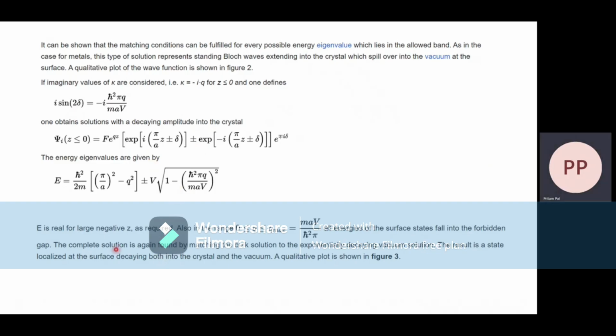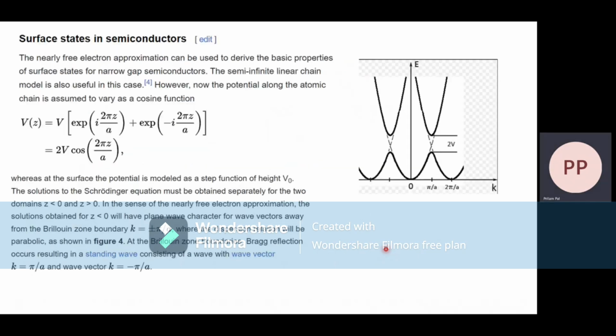So E is real for large negative z, as required. Also in the range of 0 less than q less than q max. Q max is basically m a v by pi h-bar squared. So all the energies of the surface states fall into the forbidden gap. The complete solution is again found by matching the bulk solution to the exponentially decaying vacuum solution, right? So the result is a state localized at the surface, decaying both into the crystal and the vacuum. So the qualitative plot is shown in figure 3.